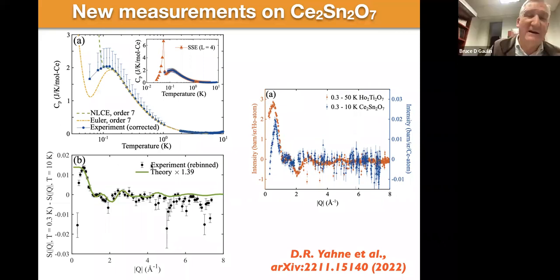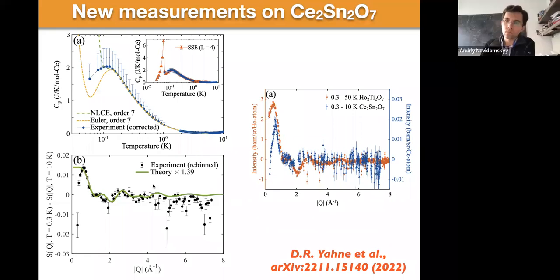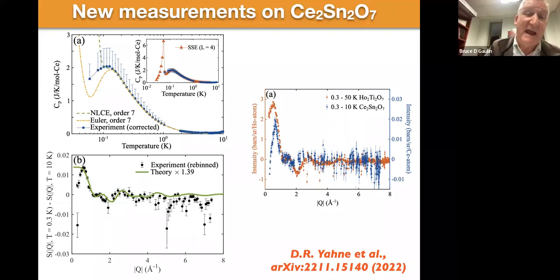The tail is actually covered in, so the parameters aren't fit to the neutron data. You generate them, and the same was true for cerium stannate. You generate them with the fits to the heat capacity and the magnetic susceptibility, and then you compare them to the diffuse neutron scattering to check on consistency. Okay, and so what I'm showing you in the bottom is really a consistency check.